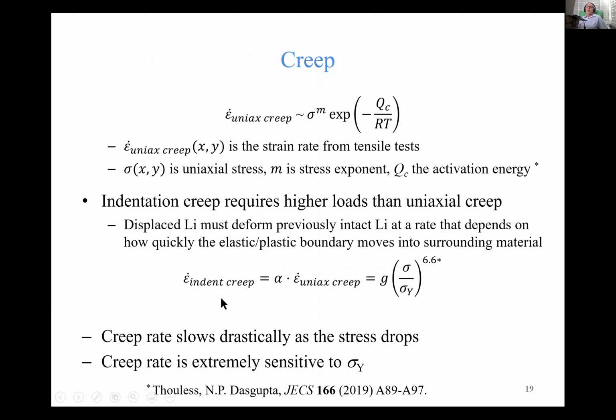Now, creep is another factor that we have to take into account, and there are creep laws that are sort of empirical that you can look up in books. This is the uniaxial creep rate, the strain rate that you get from tensile tests that are done in the lab, such as those done at Michigan. Sigma, which can depend on local position X and Y, is the uniaxial stress. M is some sort of empirical stress exponent, and Q is an activation energy. And again, this is coming from Dasgupta.